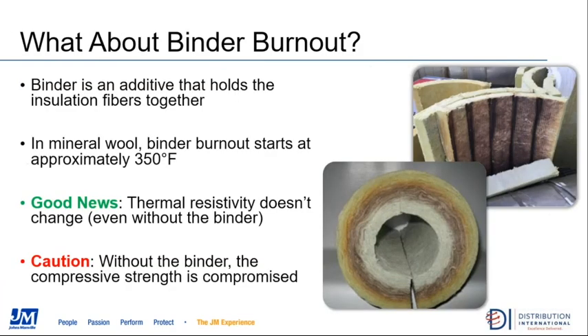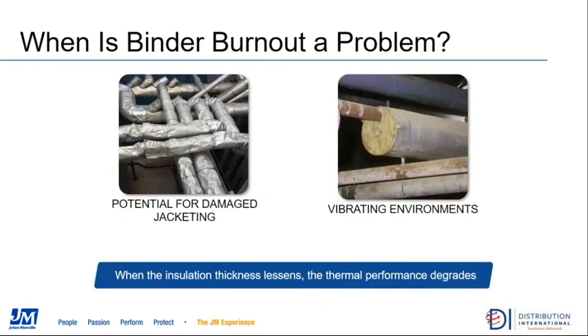No, binder. So one of the things mineral wool does have, because it's fibrous, is an organic binder. Organic binder means at temperatures of 350 and above, it's going to start to burn out. The good news is the thermal conductivity doesn't change without the binder, but the binder is what holds the fibers together, so the compressive strength may be compromised. Also, in any environments where there's high vibration, where there's no binder holding the fibers together, the fibers will tend to settle, as you'll see in the picture on the right. So that pipe there is very well insulated on the bottom, but not so much on the top anymore. And that's because the binder wasn't there to hold the fibers in the high vibration environment.